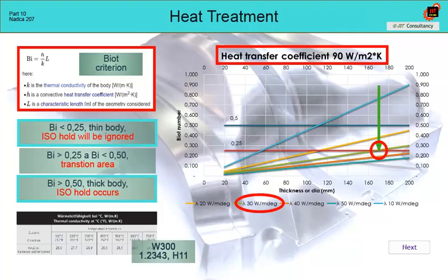For all parts with a smaller characteristic dimension, the isothermal hold is unnecessary and most likely will not occur. For parts with a characteristic dimension above 170 millimeters, an ISO hold is required and is likely to occur in automatic process control. The advantage is that if we have a sophisticated furnace control system and evaluate Ts and Tc, we do not have to solve this problem. So we can always use a program with 5 steps, and the control system of the furnace will decide whether the ISO hold occurs or not.